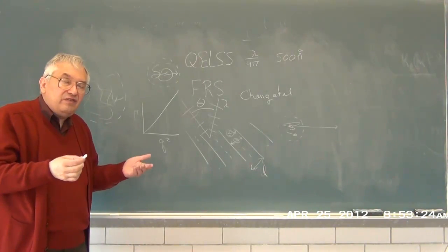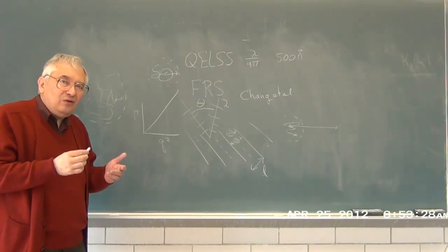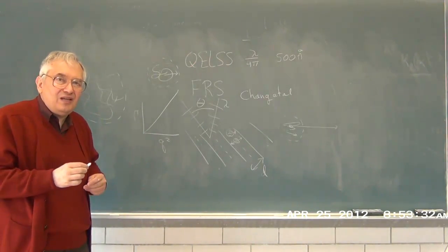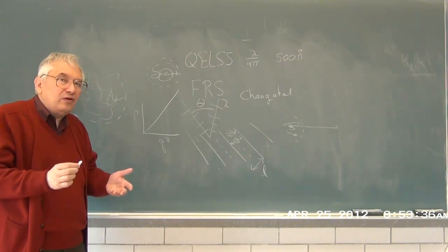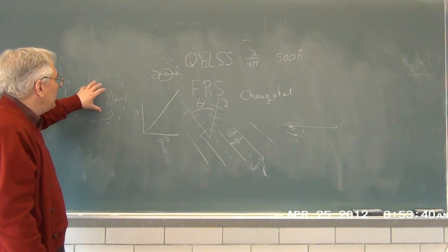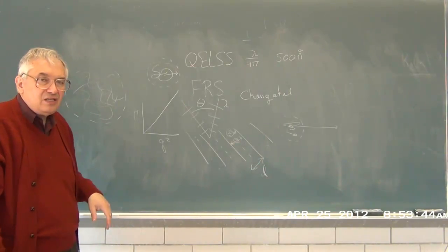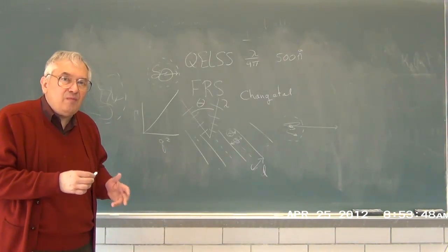We put in it spheres of different sizes, and we discover how fast the sphere of each different size diffuse. And therefore, we can infer what size of polystyrene sphere would give us a relaxation rate about as fast as the relaxation rate we see as the ultra-slow HPC mode.